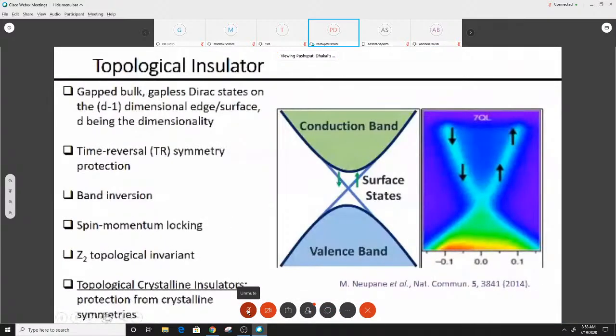Before going into the results, I want to discuss some theoretical background, starting from topological insulators. These are materials which are analogous to band insulators in the bulk. However, on the surface, they have gapless surface states within the band inverted valence and conduction band. These surface states are linearly dispersing in momentum space, and the spin states are locked to the momentum direction. The surface states are protected by time reversal symmetry, and they are robust against perturbations as long as this symmetry remains protected. And these topological insulators are characterized by the Z2 topological invariant.